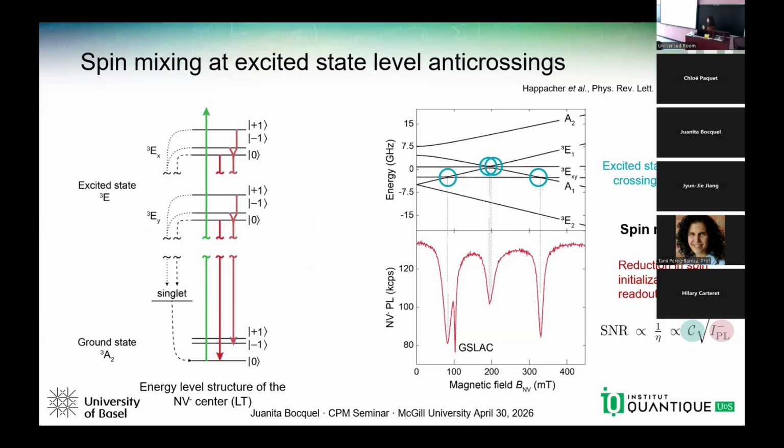So if you think about using those NV centers in this particular region, what you will see is a really strong reduction in spin polarization, with an overall loss in sensitivity to external fields. Actually, for sensitivity it is sort of a double penalty, because you lose both contrast and the full number of counts that you are extracting from the system.